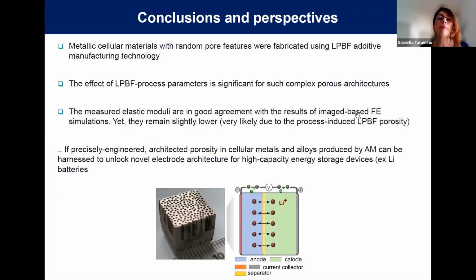In the end, I want to summarize the main result of this work. So essentially, we transferred the method we have developed for the generation of random porous material to metallic cellular materials produced by laser powder bed fusion additive manufacturing. We have seen that the manufacturing of complex porous architecture is tricky with this process, and we have to account for a breadth of parameters which is generally neglected in other simpler microstructures. And finally, the comparison between the experiment and the simulation is pretty satisfactory.